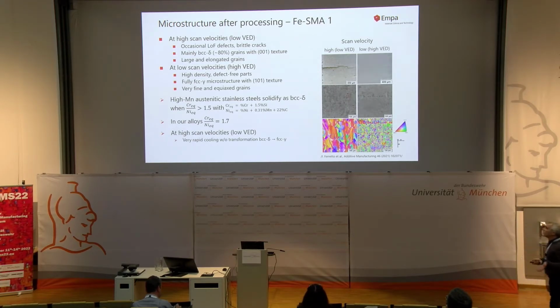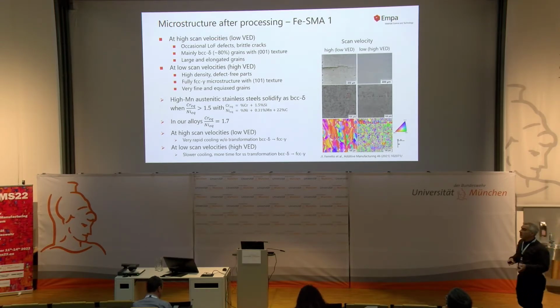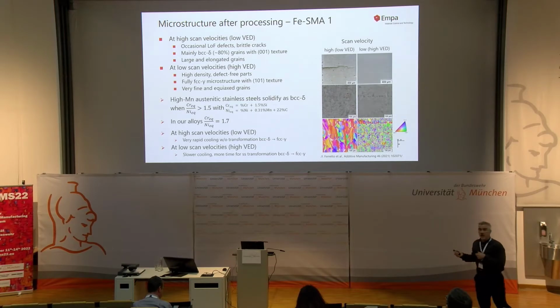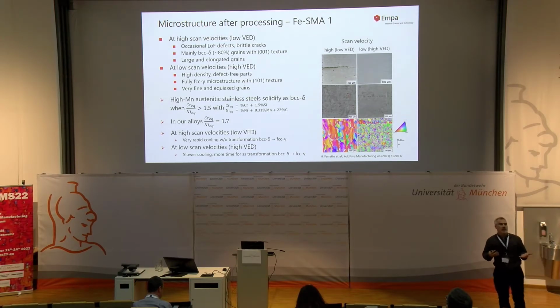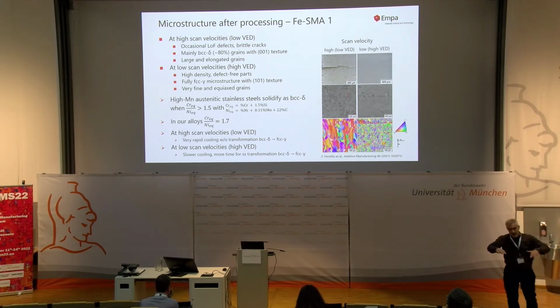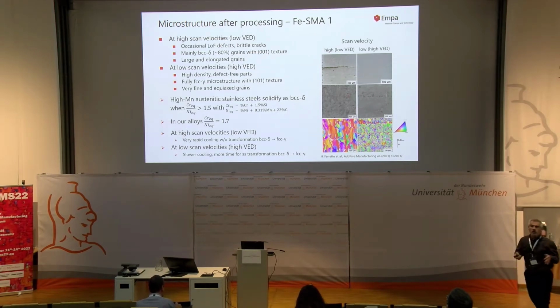So at high scan velocities, we just quench from the delta field. There is no time for any transformation. However, if we go to lower scan velocities, so if we put more energy into it, so we slow down the whole cooling, we give it more time for the transformation, and therefore we see this very typical microstructure.